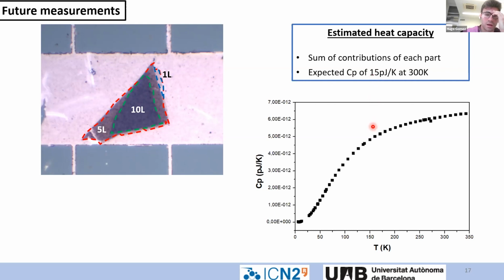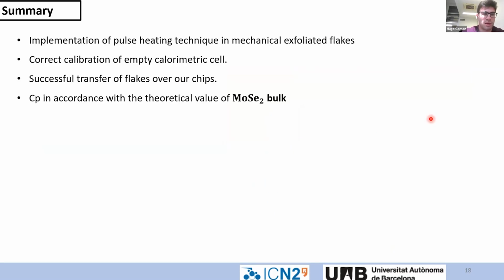And the bulk material heat capacity is reported with this value. So, just to sum up, we have implemented this pulse heating technique in mechanically exfoliated flakes. We have done it correctly. We have also done a correct calibration of our empty calorimetric cell, and a successful transfer of our flakes over our chips, and the heat capacity that we are measuring is in accordance with the theoretical value of